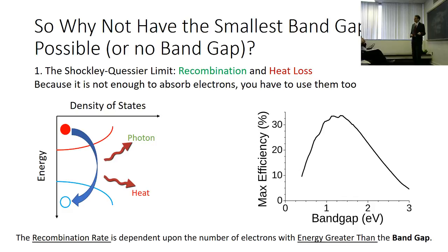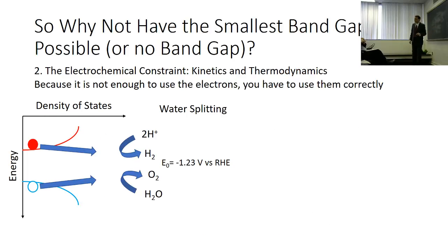So you want to balance the band gap in terms of absorption and recombination. Shockley and Queisser studied this, and found that the optimum band gap for absorbing light, with a lot of other stipulations, for a solar cell is between 1.2 and 1.4 electron volts. This is our first reason we want to tune the band gap, or care about it at all. The second reason is if you want to do photoelectrochemistry, you want that electron to power a reaction, so you have to consider the energy barrier to that reaction. In water splitting, there's a certain energy barrier you have to overcome with your electron in the conduction band.